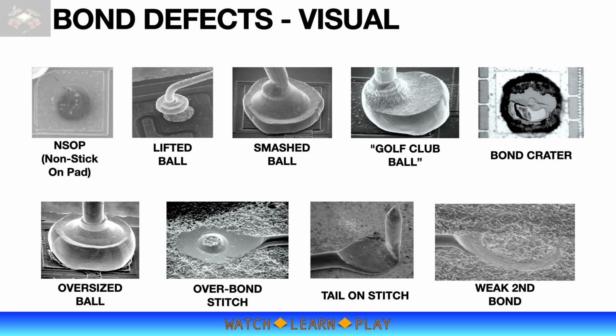Several factors may contribute to NSOP and lifted ball problems, such as bond parameters not optimized, worn out capillary, loose transducer clamp screw, or transducer not being calibrated properly. It is also possible that the lead frame or substrate did not sit properly on the pivots, causing vibration during the bonding process. Bond pad contamination like silicon dust on the bond pad, or even deep probe mark and bond pad corrosion, is a possibility.